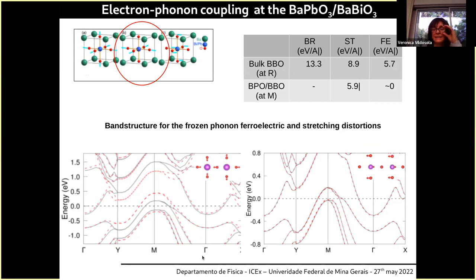So we will apply the same technique to calculate the interfacial phonon modes and to observe the shifting and the electron-phonon coupling of the system. Here we studied the stretching mode that is like the breathing distortion but in two dimensions, and here I show how the band structure changes when we apply a distortion according to the stretching mode, which is indicated in the inset, and we measure the shift in energy of the electrons. This is for the stretching mode, and we also observe that the ferroelectric mode in two dimensions doesn't induce any effect in the electrons.